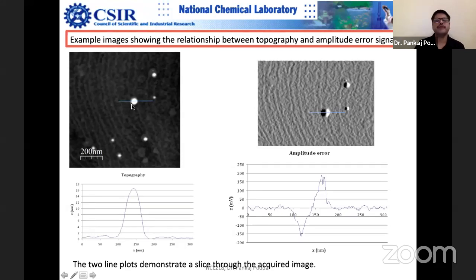But in fact, if there's any sharp jump and if the gain is not very high, you can see that there is amplitude error also when this tip tries to go. Now you can see this signal is in millivolt. It is not in nanometer, because this is a voltage reading, a reading for the scanner moving up and down. The scanner is already calibrated in distance, so you get the voltage, and you get the reading in distance.